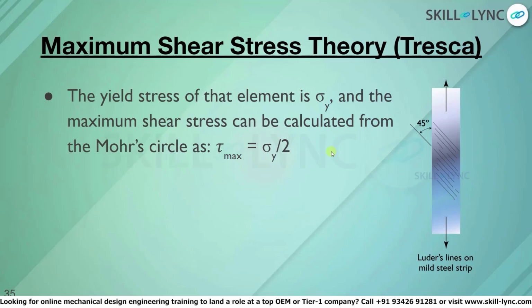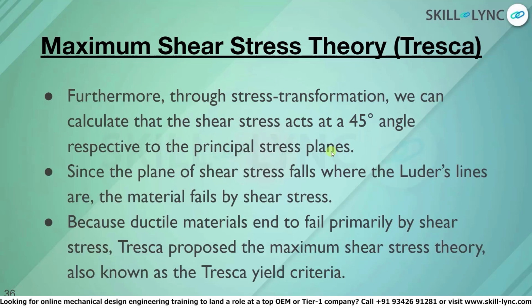Now the yield stress of that element is sigma y, and the maximum shear stress can be calculated from the Mohr circle as tau max is equal to sigma y by 2. Furthermore, through stress transformation, we can calculate that the shear stress acts at a 45 degree angle with respect to the principal stress planes. Since the plane of shear stress falls where the Luder's lines are, the material fails by shear stress. If we do the calculation, we will see that the shear stress acts at a 45 degree angle to the principal stress plane. And since this angle coincides with that of the Luder line, the material will fail by shear stress.